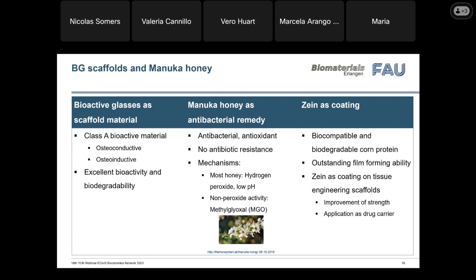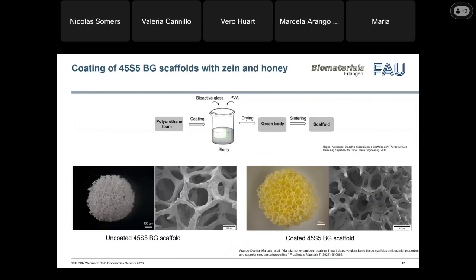And then we have zein, which is a corn protein, and here it was used to help carry the honey as well. It was used because it has a great film forming ability. The production of the scaffolds was through the foam replica technique. In here, polyurethane foam is dipped in a slurry containing bioactive glass powder and a binder, in this case PVA. And then this is sintered, of course first to burn out the foam and then to densify the structure.